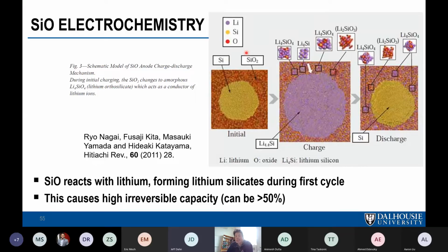No, it's not. It's terrible. Yeah, it's an interesting result, but practically speaking, the reason you add oxygen is to lower the volume expansion. But on the first lithiation, it doesn't lower the volume expansion compared to pure silicon at all. It has no effect. So that's a bad thing about SiO compared to, for instance, an alloy, which would limit the volume expansion because you have a completely inactive phase. So anyways, that's a good exercise to do.